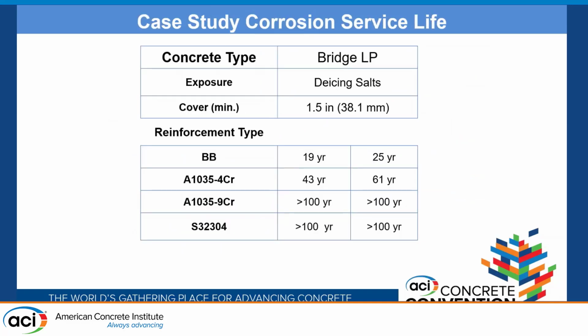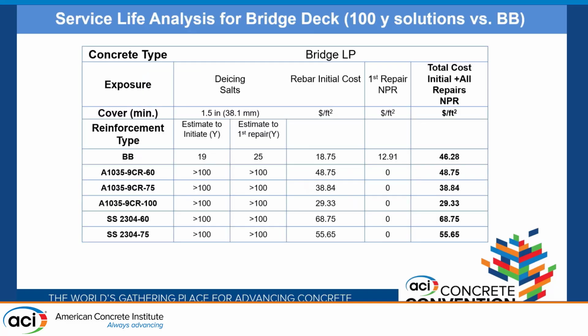Once again, looking at this particular example, the black bar had 19 years with the propagation 25 years. The 4% chrome 43 to 61, but once again you can increase cover in both of those and get a little bit better performance. And of course the high chrome and the stainless steel did much better.